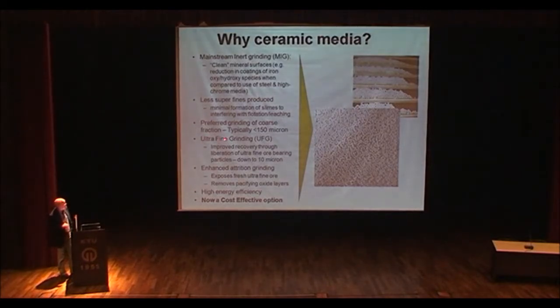And it will in that time go from around 150 micron down to 10 micron. That'll depend on the work index of the material and that sort of thing, but that's what they're doing in the platinum industry. It's a single pass, and what's happening now is they've suddenly got a whole new population of available sulfides, which weren't there before. They were milling to 35, 40 micron, and these little particles of sulfide were lost. They were going out of the tailings. Suddenly these can be recovered without having to retreat your tailings.